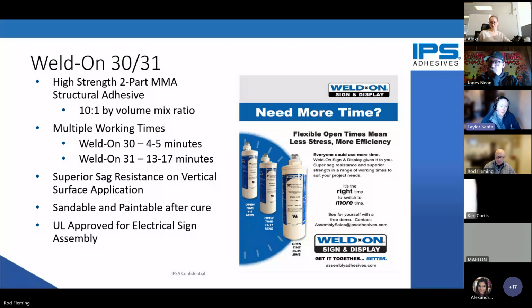Another benefit of using the Weld-On 30 and 31 is this material is actually, once it's cured, sandable and paintable. So if you have an open seam with these bondings that you're doing, you didn't quite get it completely cured out, you can just sand it down to have a smooth finish. Then you can paint right over it if you need to have the same color all the way through. I've actually seen some people in the field, if they didn't have Bondo on hand, use this product as Bondo, which works very, very well.